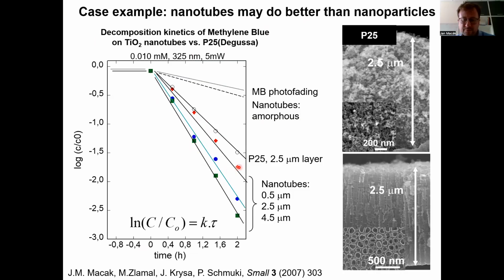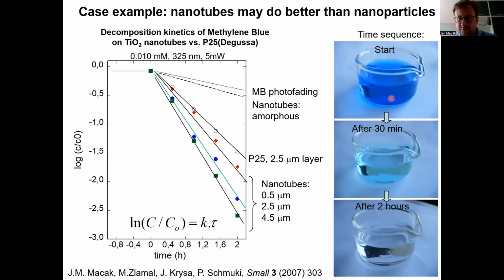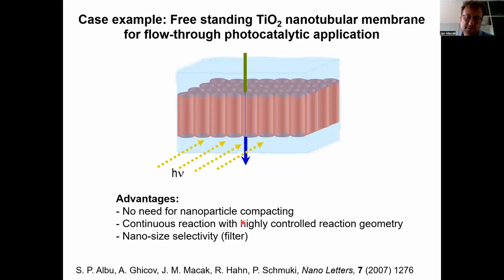And when you do the comparison with the particles and tubes, you end up with a finding that the tubes do better than particles, which is sad for the nanoparticulate people, but good for the nanotube guys, because in principle, it tells you that if you take nanoparticulate layers like P25 compacted into the same thicknesses of the tubes, there is always a slightly higher chance for photocatalysis to be better on the tubes, probably because of the opening of the tubes and higher surface area available, and also diffusional aspects play a role. So this is just a drawing of what happens with the blue dye in time. It gets decolored faster with the tubes than with the particles.